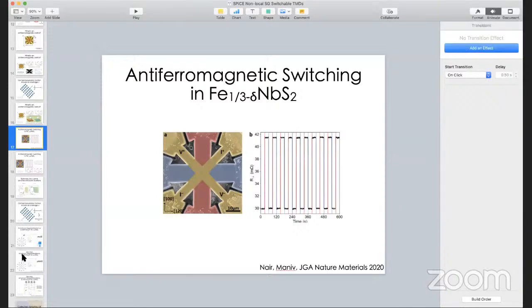Okay, some question. I am trying to understand the coexistence of these two order parameters. Is it possible that you have some main component in the same ion, which is fixed by a strong antiferromagnetic interaction, but another one which is fixed by some kind of anisotropy, can be accidentally directed maybe perpendicular to the main component, and then you will have something like coexistence of two order parameters on the same ion, like spin glass for some small component and antiferromagnetic order on another one. It is possible if you have very special anisotropy, if you have a few minima of anisotropy along one direction, then you will have such kind of behavior.